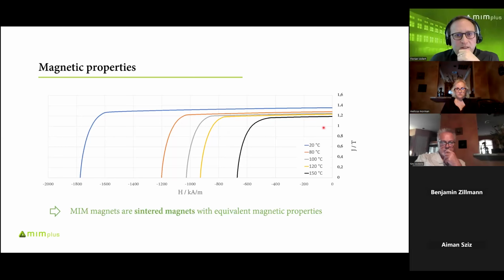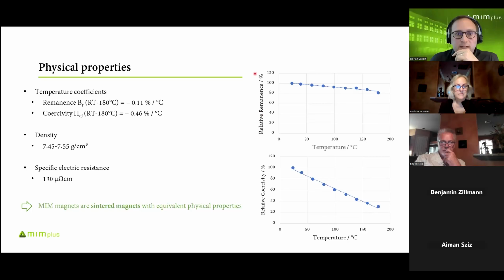And you see the demagnetization curves at elevated temperatures. We are also able to measure them. When you take the remanence, which is of course decreasing with increasing temperature, and also the coercivity, which is decreasing, and plot the relative remanence and the relative coercivity over the temperature, you also get a linear correlation. From the slope of that line, we get the temperature coefficients: for the remanence, minus 0.11% for each degree C or Kelvin. And for coercivity, it's usually higher, which is here 0.46% for each Kelvin.